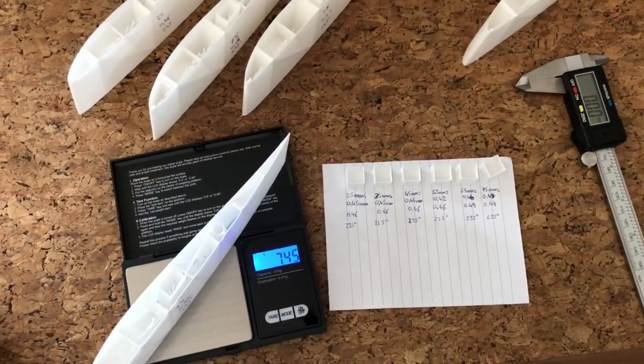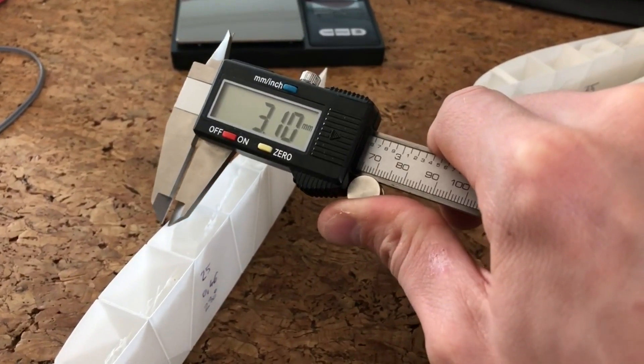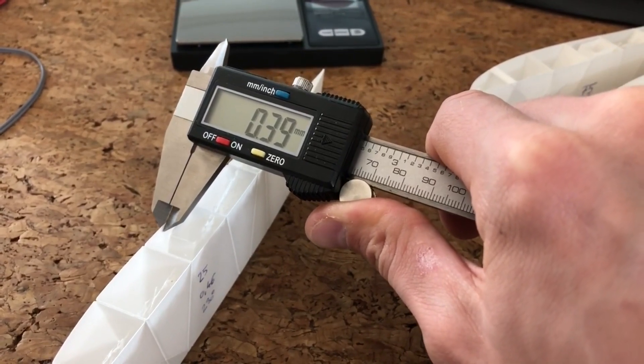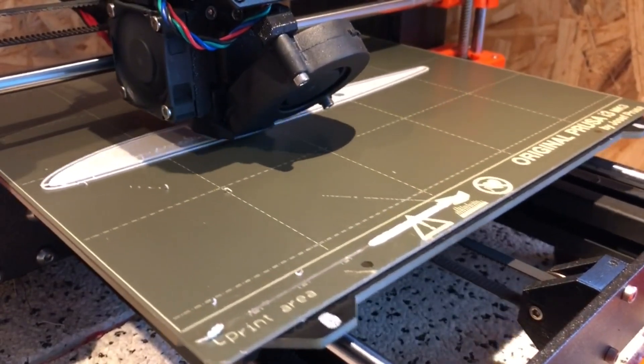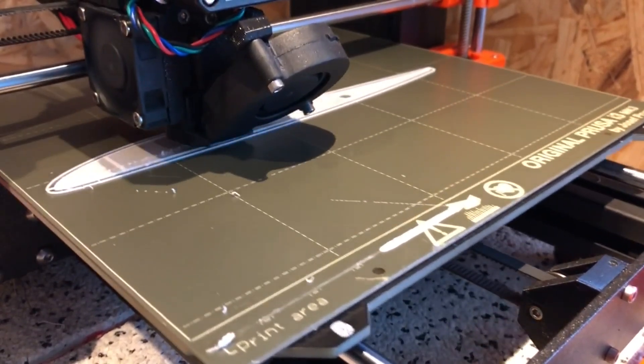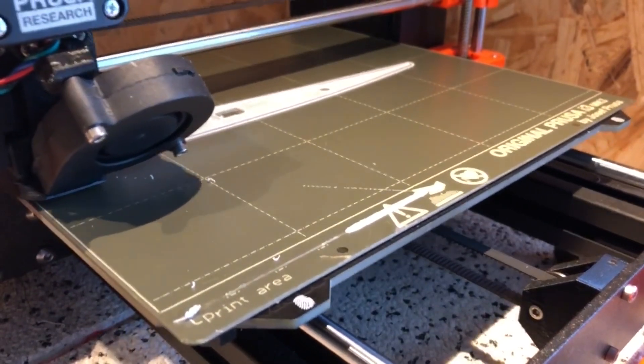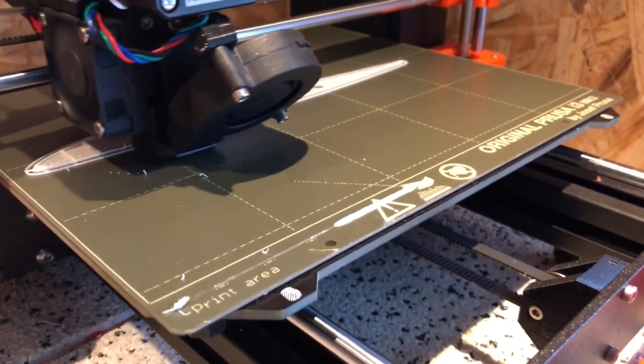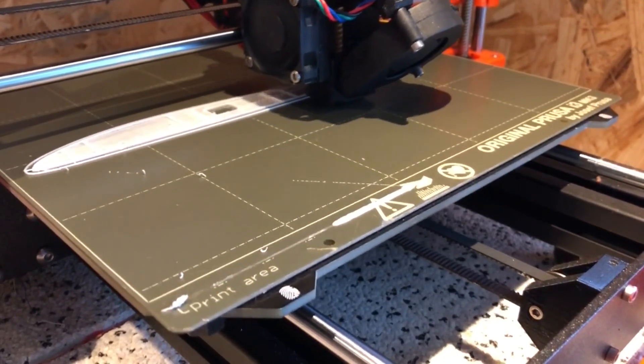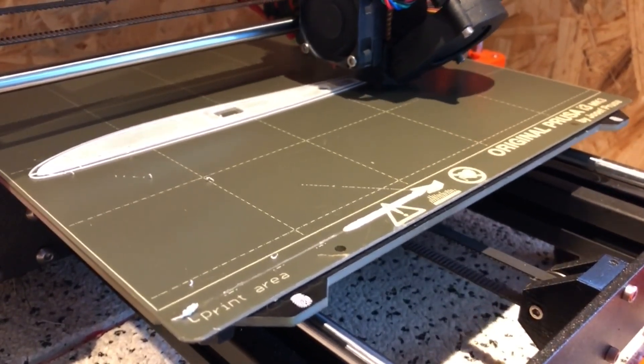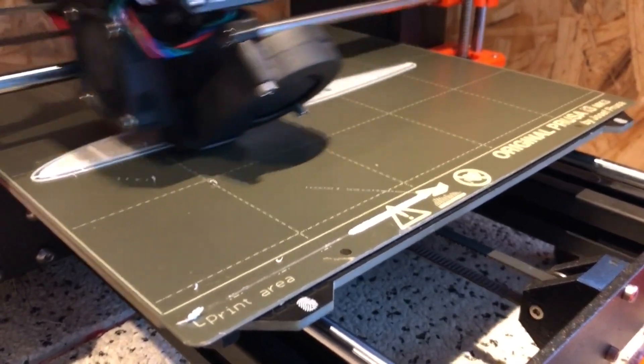I first printed the part with my default lightweight PLA profile and it came out quite a lot too thin. The average wall thickness, which I measure on six different points of the airfoil, was only 0.4 mm when it should have been 0.45 mm. I guess that's due to a slight change in ColorFabb's lightweight PLA which I noticed a few months before lightweight PLA-HT hit the market. It seemed that the filament doesn't expand as much anymore, and I don't know if anyone else recognized, but I did as I used G-codes to print the same parts on and on.